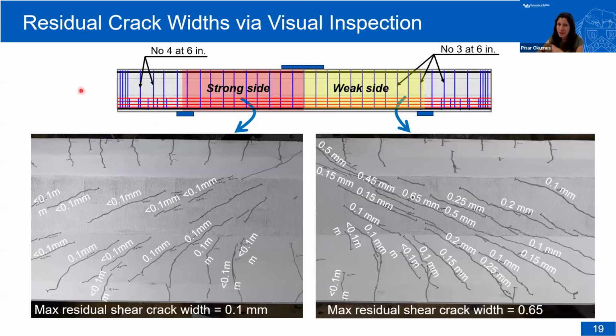These were the crack widths that we collected. So we did see those shear cracks. These are the residual crack widths. That's why they're small. But we collected that data from the weak side and the strong side. And then you could see the doubling the reinforcement really does help with the crack width. So much smaller cracking on the strong side of the beam.